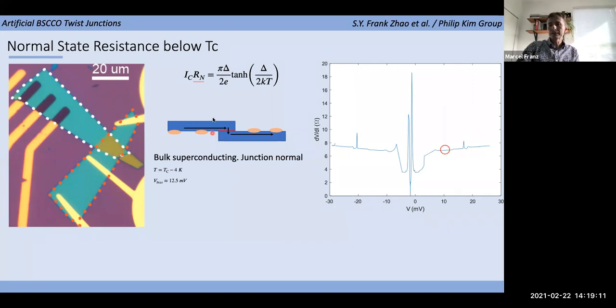The thickness is about 10 to 20 monolayers, and they assemble them with various twist angles and measure the Josephson current through this twisted junction, and they find some interesting signatures that I'm not allowed to show you because this is unpublished research, but we're working with them to see if they may already have some evidence for this spontaneous time reversal symmetry breaking.